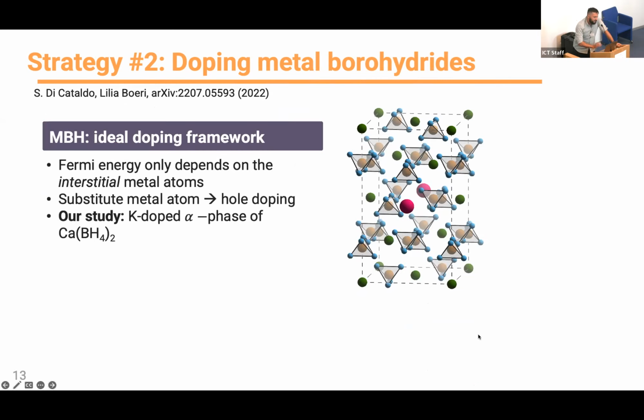Essentially, because of this peculiar charge transfer between the metal atom and the BH4 molecule, the position of the Fermi energy depends on the interstitial metal atoms. By replacing a portion of the metal atoms, we can tune almost freely the position of the Fermi energy. So in our study, what we did was replace a fraction of calcium in the alpha phase of calcium borohydride with a tiny amount of potassium. Potassium has valence 1, calcium has valence 2. So for every calcium we replace, we inject 1 hole into the crystal.